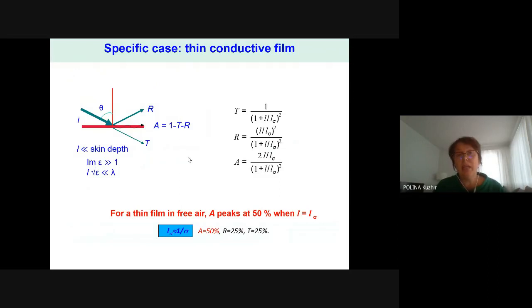There is really an exceptional case: the case of a thin conductive film, whose thickness is much smaller than the skin depth. If we address a wavelength much larger than the film thickness, and this film is made of highly conductive material, we could expect for a particular thickness a very interesting electromagnetic response.